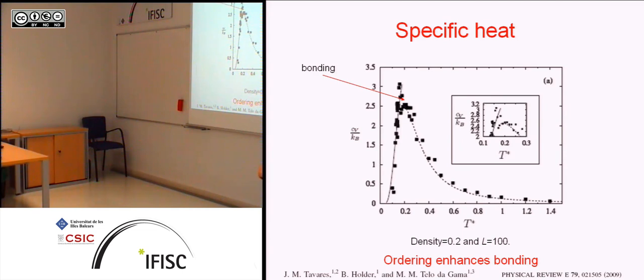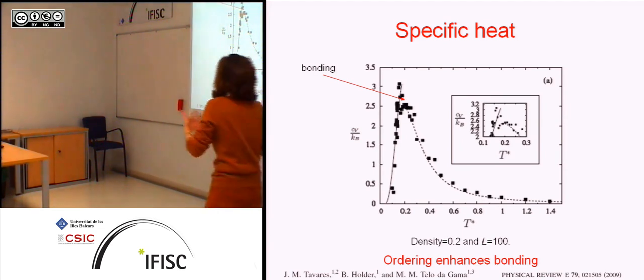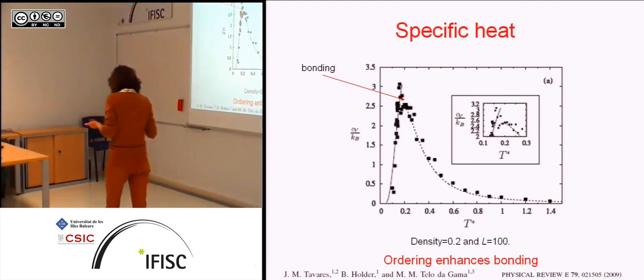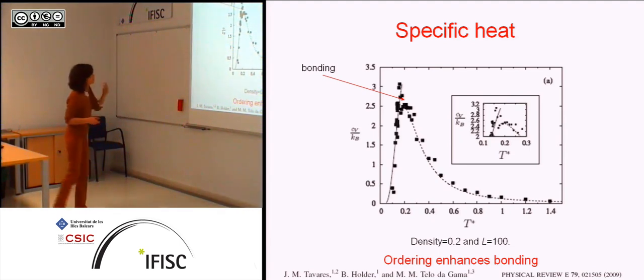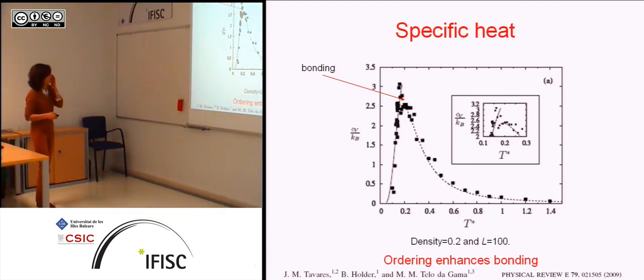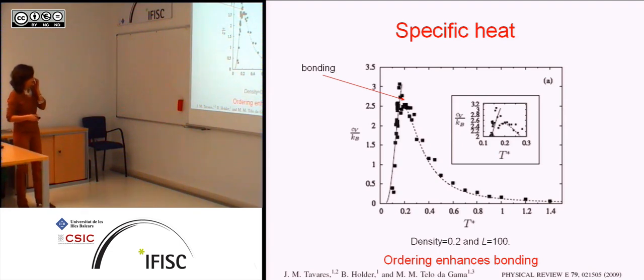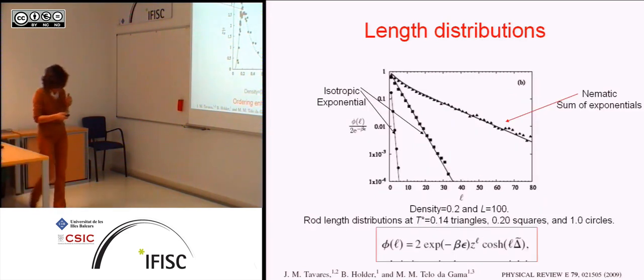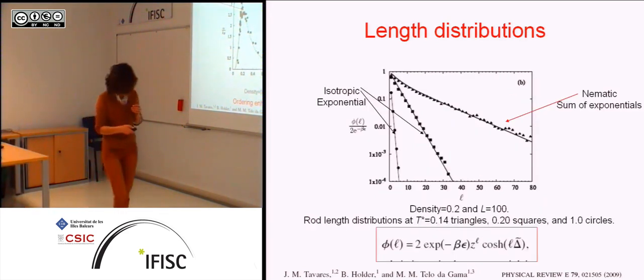And the dots are simulations on a square lattice. The curves are this mean field theory, which on this scale gives you the order of magnitude, so we thought we understood what's going on. And in fact, we concluded that at least at these intermediate, still low densities, ordering enhances bonding, in the sense that it occurs before, and then the specific heat even increases at the order transition.